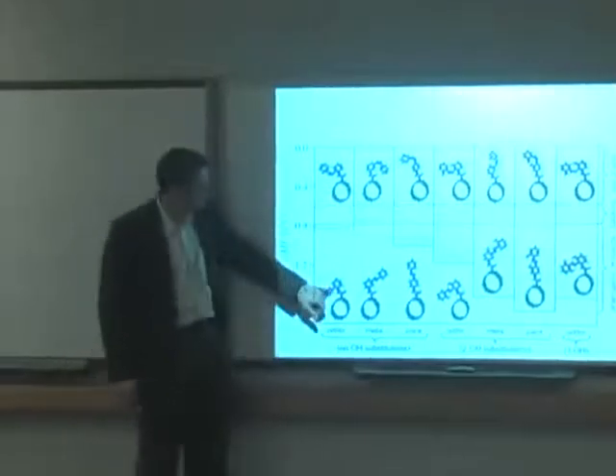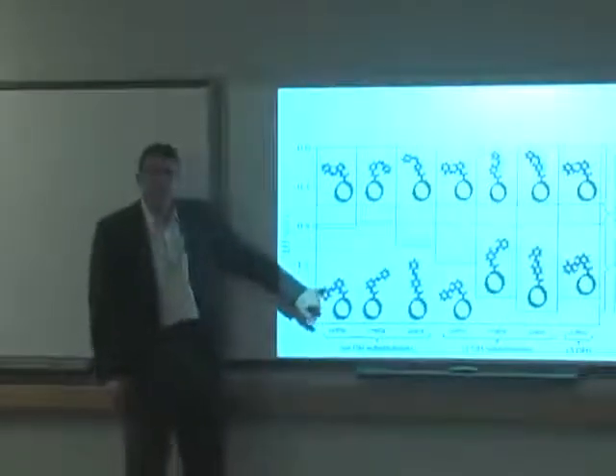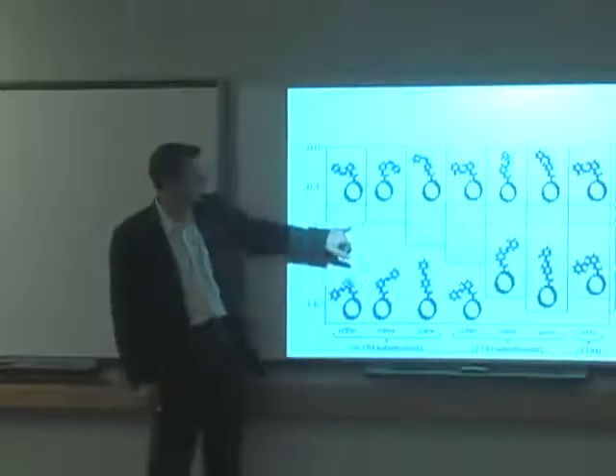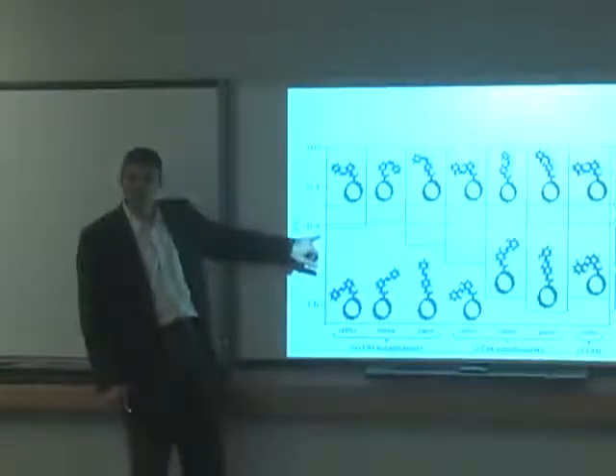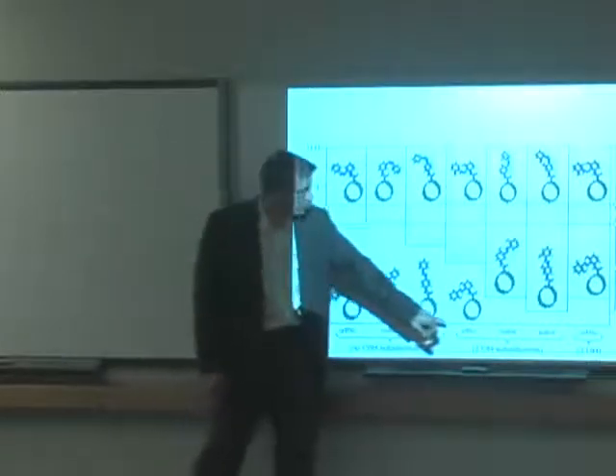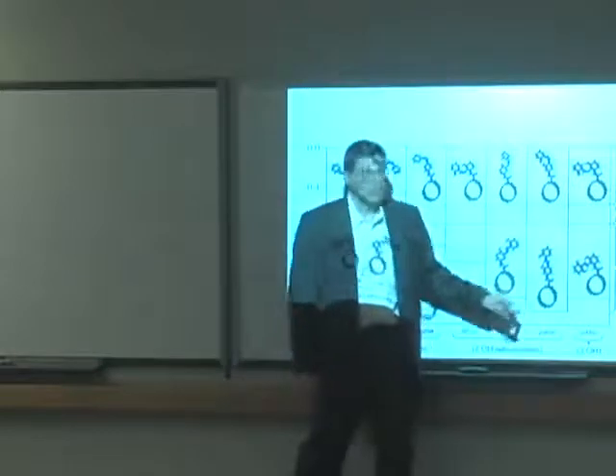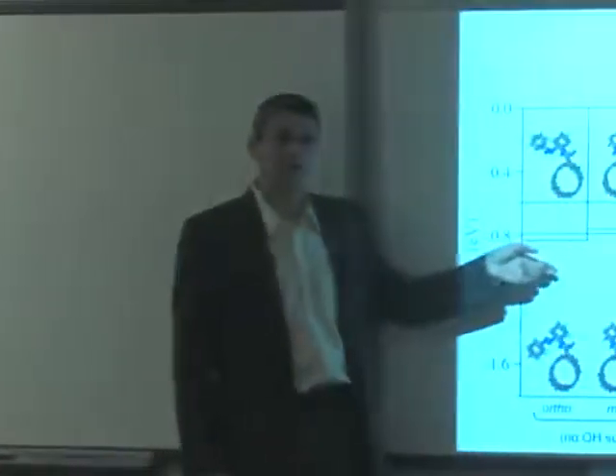And you can see that that's worth about a couple of tenths of an electron volt increase in the stored energy per molecule. But now it gets really interesting when I start putting those hydroxyl groups in different positions. I can take advantage of these chemistries, as I just described, and actually get a factor of 2.5 times the energy storage per molecule when I do it, say, in this way, or really pretty much any of these ways.